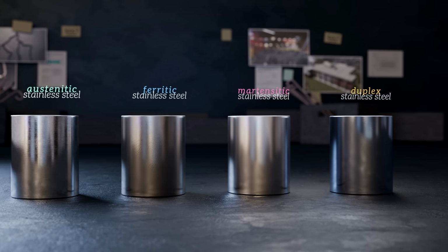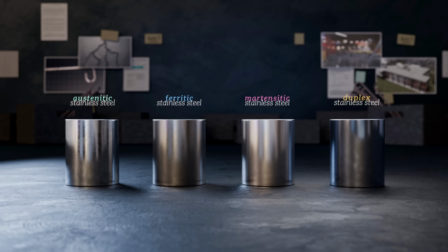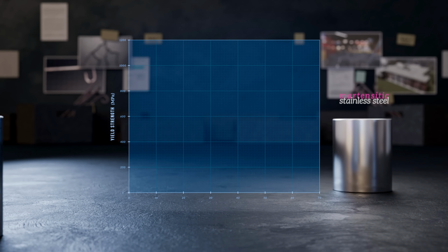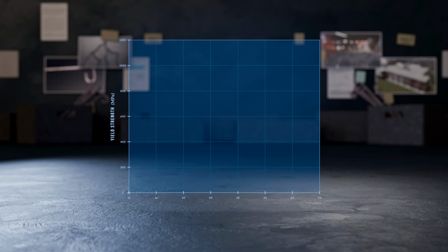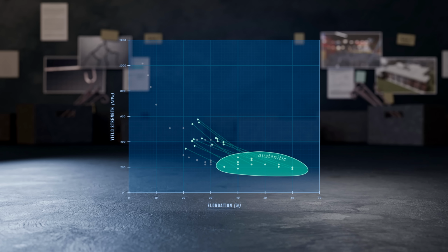We can compare the mechanical properties of different stainless steels by plotting yield strength, the stress at which the steel begins to deform permanently, against elongation, a measure of how much the material can stretch before it fractures. Austenitic stainless steels tend to have moderate yield strength and high elongation, although when cold worked, their yield strength rises significantly due to strain hardening, at the cost of reduced ductility.